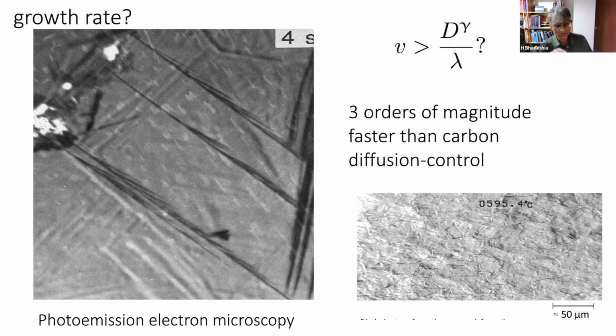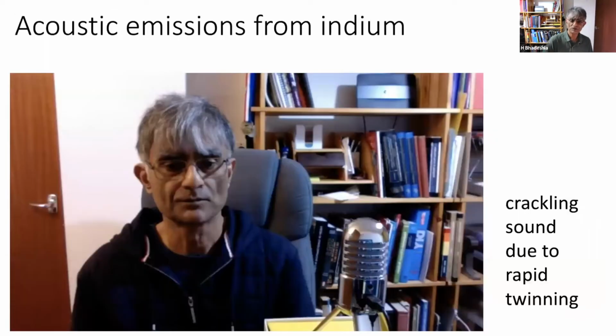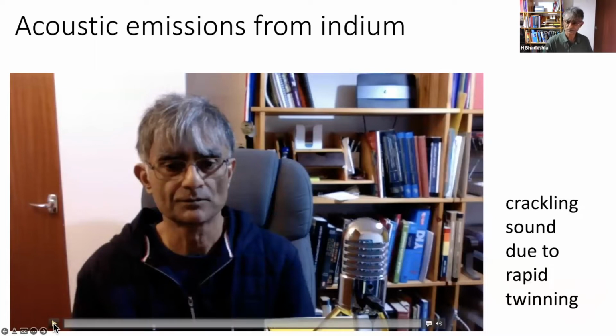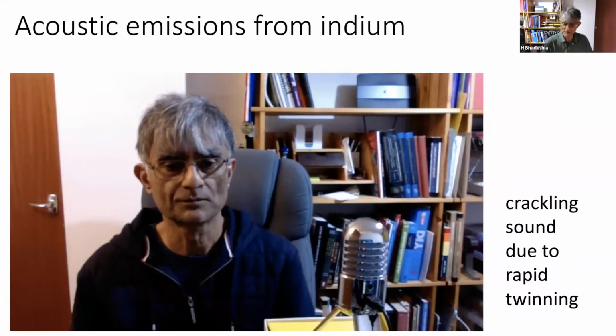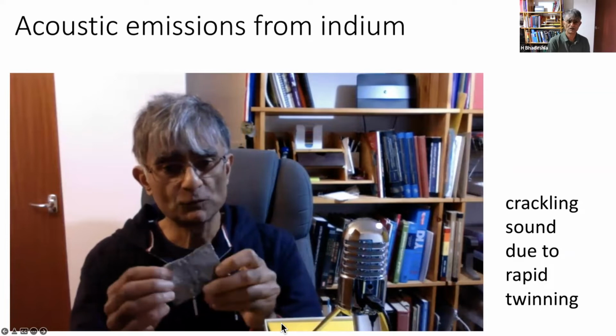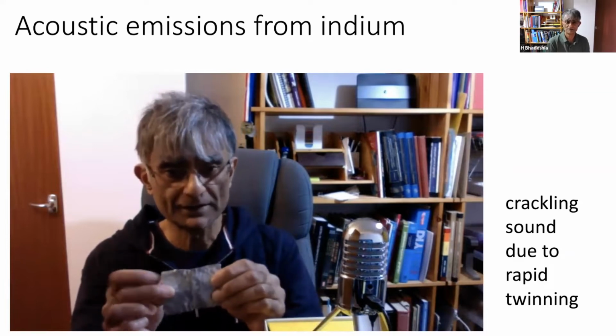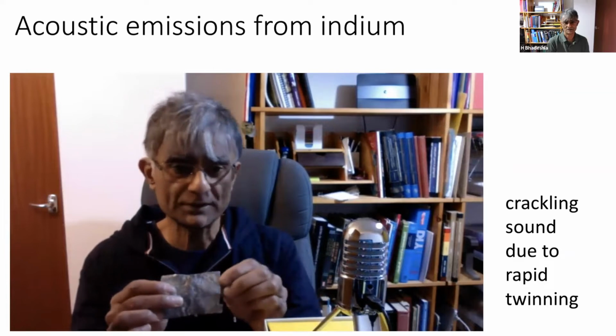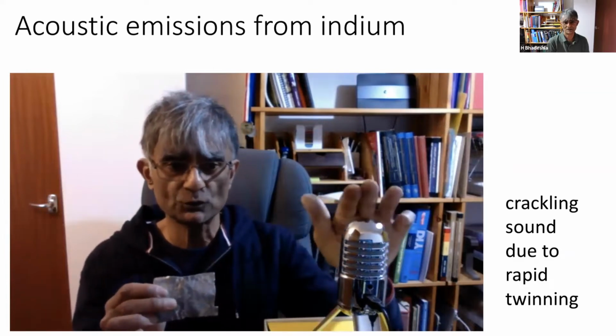But if you argue that this is a diffusionless transformation, you also make various other predictions. And one of those is very interesting. So I'm going to show you a little movie of mechanical twinning happening in indium metal. Indium because I can recrystallize it at 100 degrees centigrade and reuse it many times, even though it's expensive. This is a piece of indium metal, which I'm going to deform. And when it deforms, it does so by mechanical twinning. And every time a twin forms rapidly, we get an acoustic emission, which I will record with this microphone.